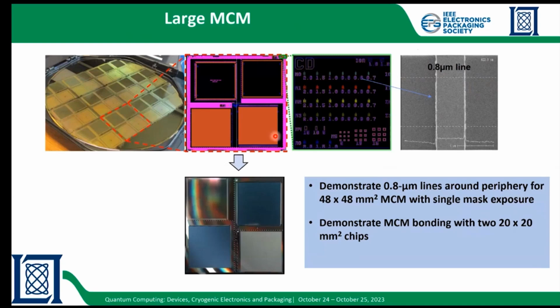There are multiple CD cells you can see over here. And these CD cells are basically confirming that we can print a 0.8 micron line. Here the image shows a 48 millimeter by 48 millimeter MCM diced out from a 200 millimeter wafer and bonded with a 20 millimeter by 20 millimeter chip.